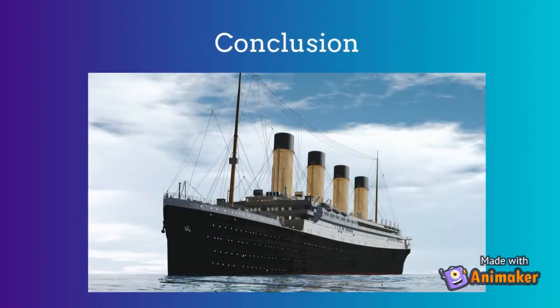In conclusion, while the steel used for the Titanic may have had a high tensile strength and toughness for the time period, it was not adequate for the conditions it would be used in, resulting in a material failure. The steel used had a low fracture toughness that resulted in brittle fracture of the material. The metal could have possibly been heat treated to improve the toughness instead of just being air-cooled and annealed. Perhaps with heat treatment, the metal could have withstood the temperatures of the water, and the tragedy of the Titanic could have been avoided.